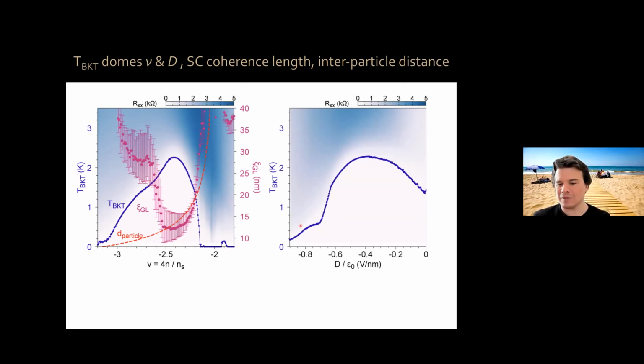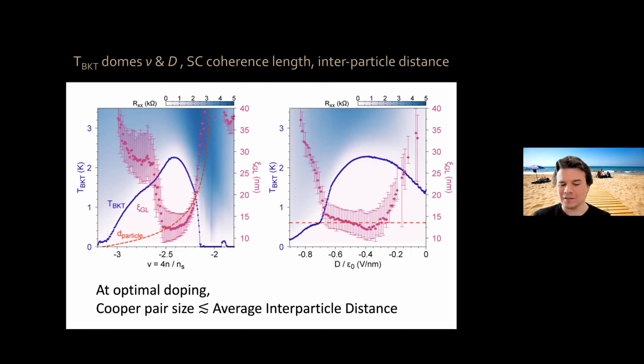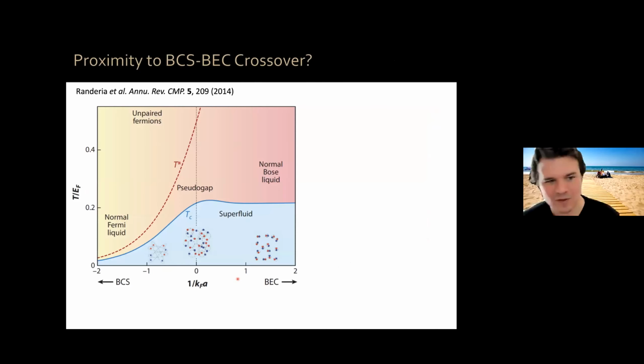Now we can do the same thing at optimal density as a function of displacement field. This is the TBKT, this is the superconducting coherence length, and this is the average interparticle distance at optimal density. So at optimal doping, the Cooper pair size is of the same order or smaller than the average interparticle distance. That immediately reminds us of what happens in the BCS to BEC crossover.